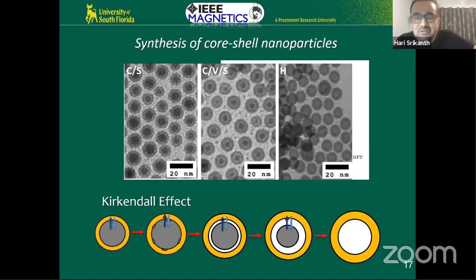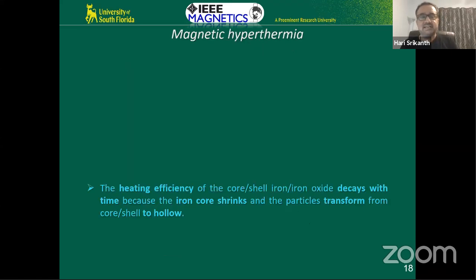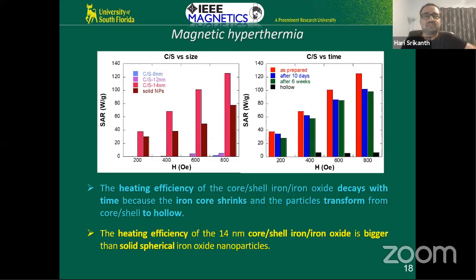Obviously, this is not good for hyperthermia because we want stable particles, right? We don't want the particles degrading over time, magnetization going down, SAR going down in an unpredictable manner over time. So it's not good for that, but it was a nice study where we were able to understand how it worked. So let me show you the SAR here. I'm going to show the SAR as histograms for easy comparison, okay? So if you look at the particle size, for example, it's clear that the original goal was achieved.